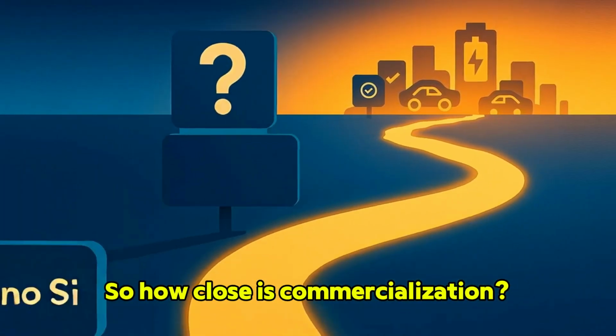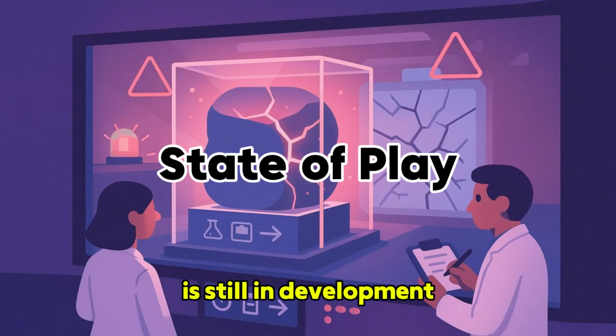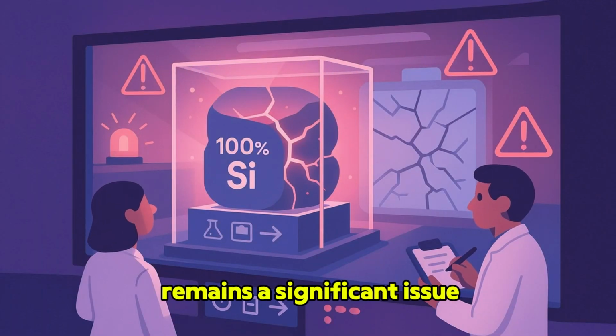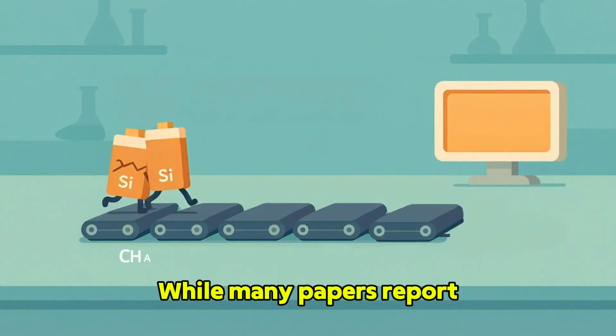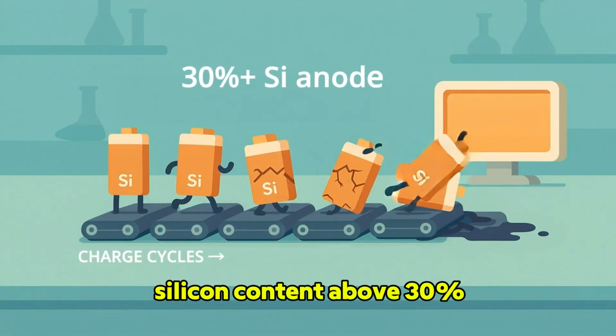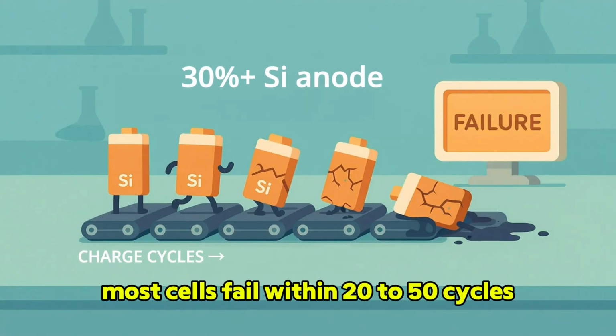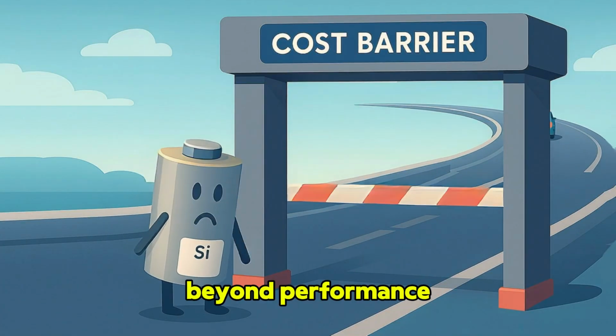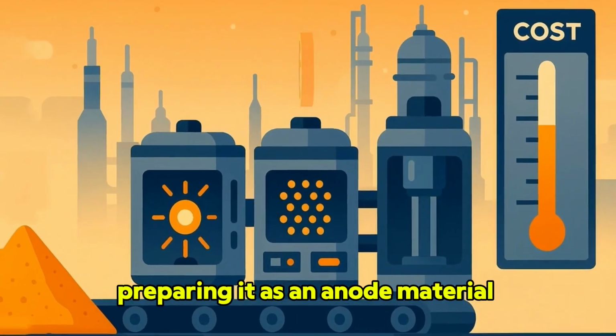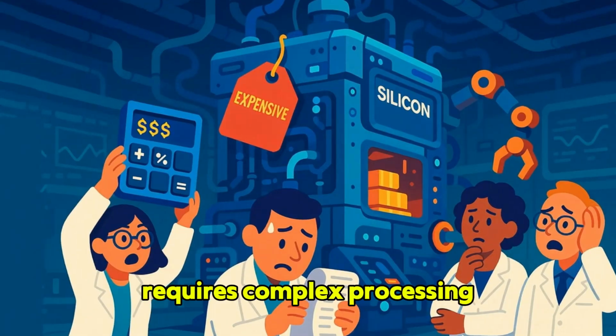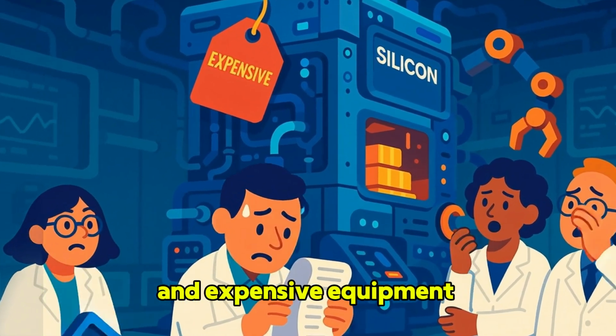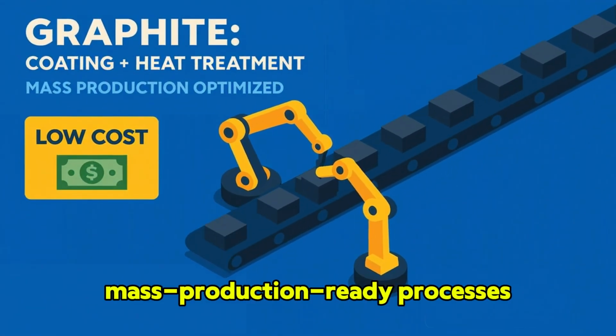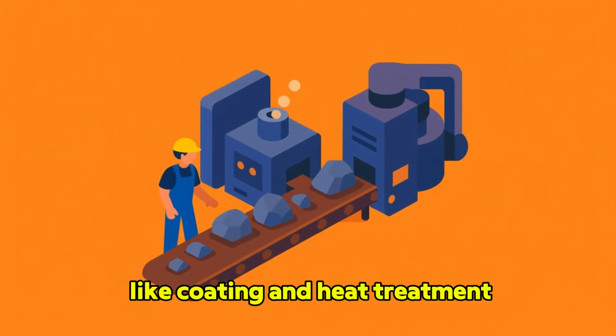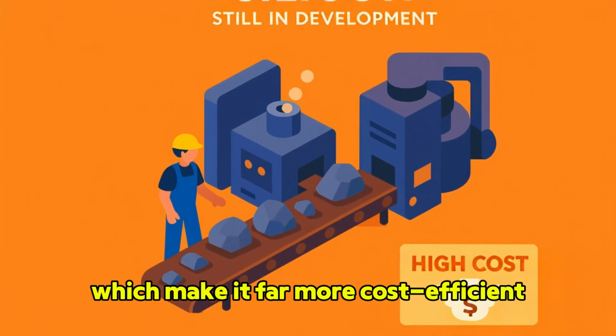So how close is commercialization? A pure silicon anode is still in development because volume expansion remains a significant issue. While many papers report silicon content above 30%, most cells fail within 20 to 50 cycles. There are also challenges beyond performance. Cost. Even though silicon is abundant, preparing it as an anode material requires complex processing and expensive equipment. Graphite, in contrast, uses well-established, mass-production-ready processes like coating and heat treatment, which make it far more cost-efficient.